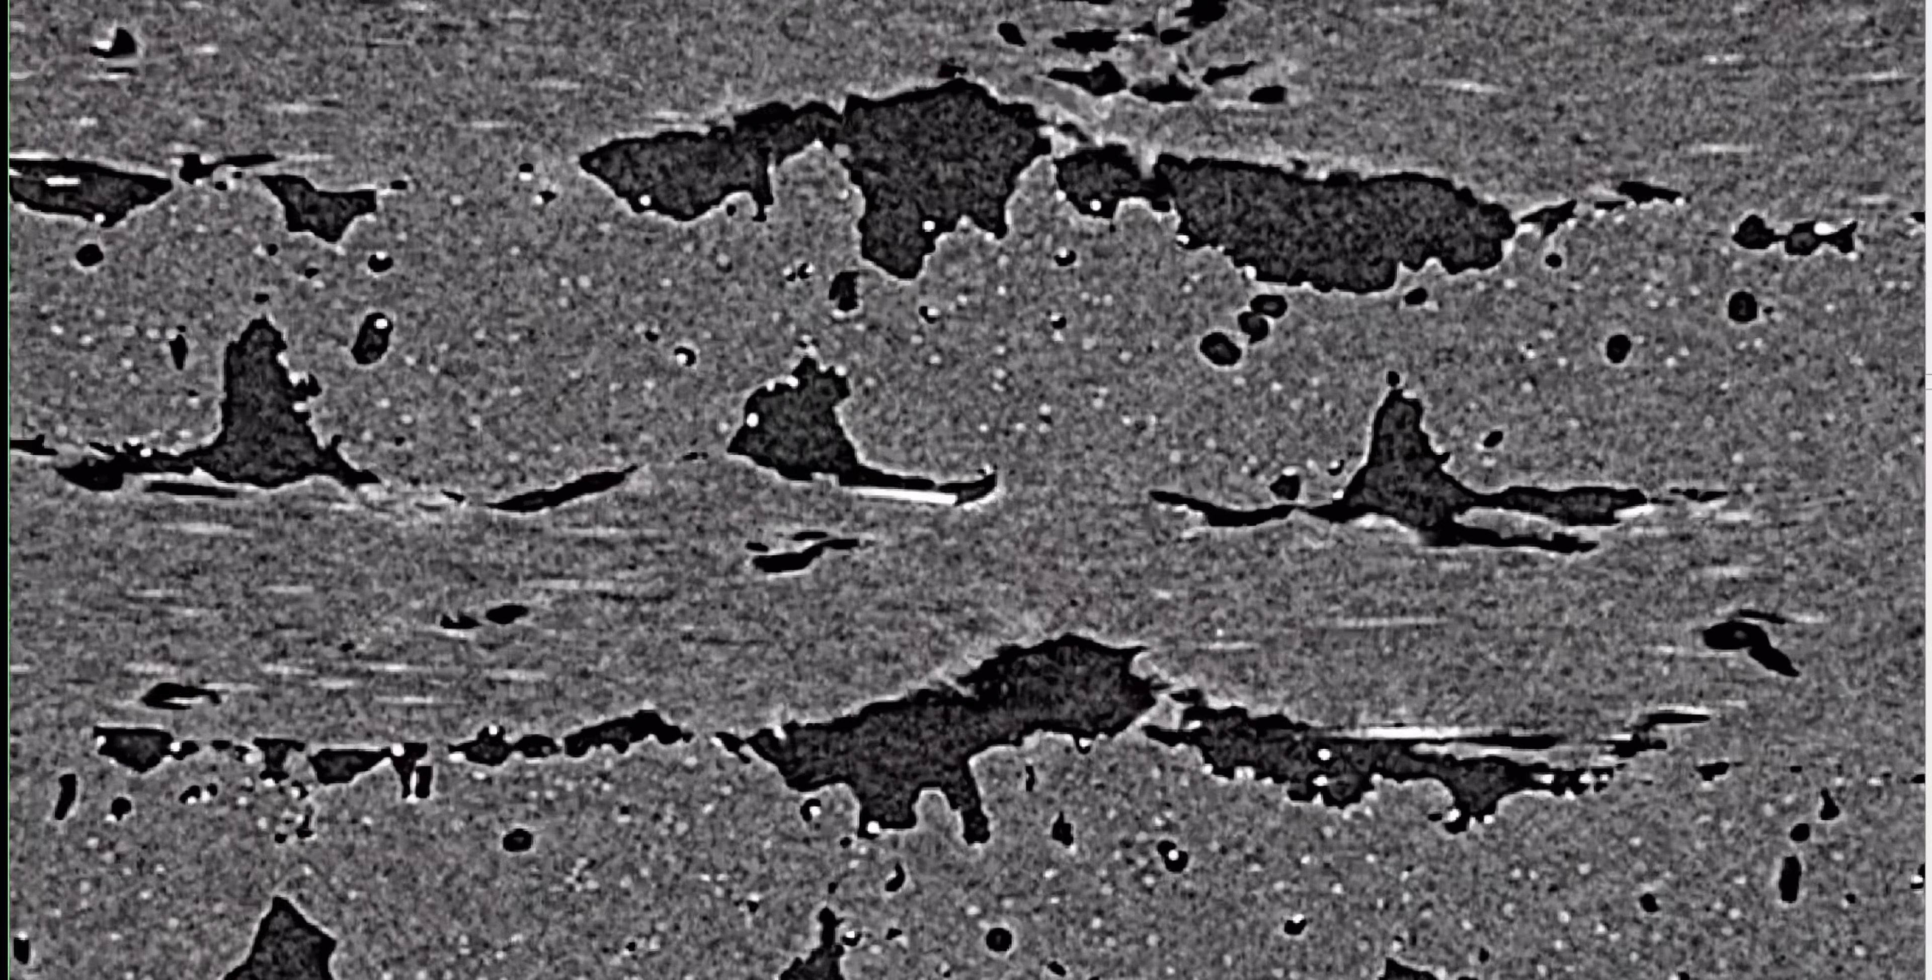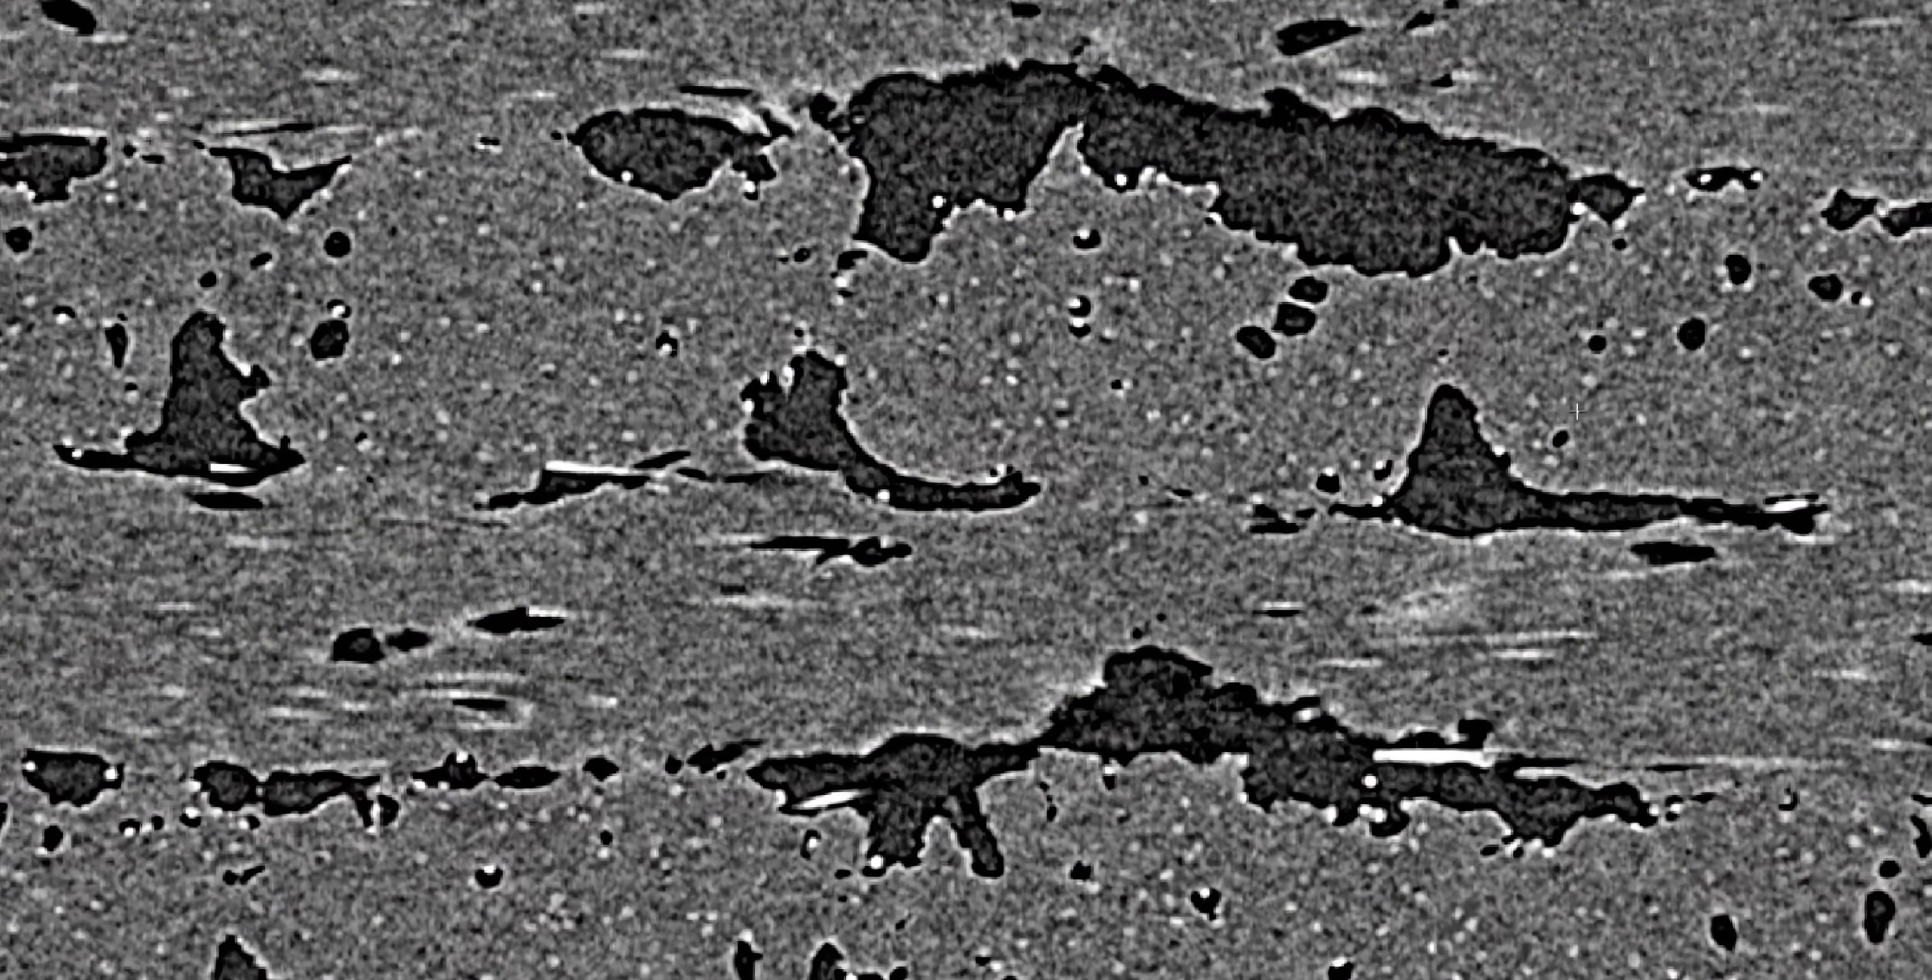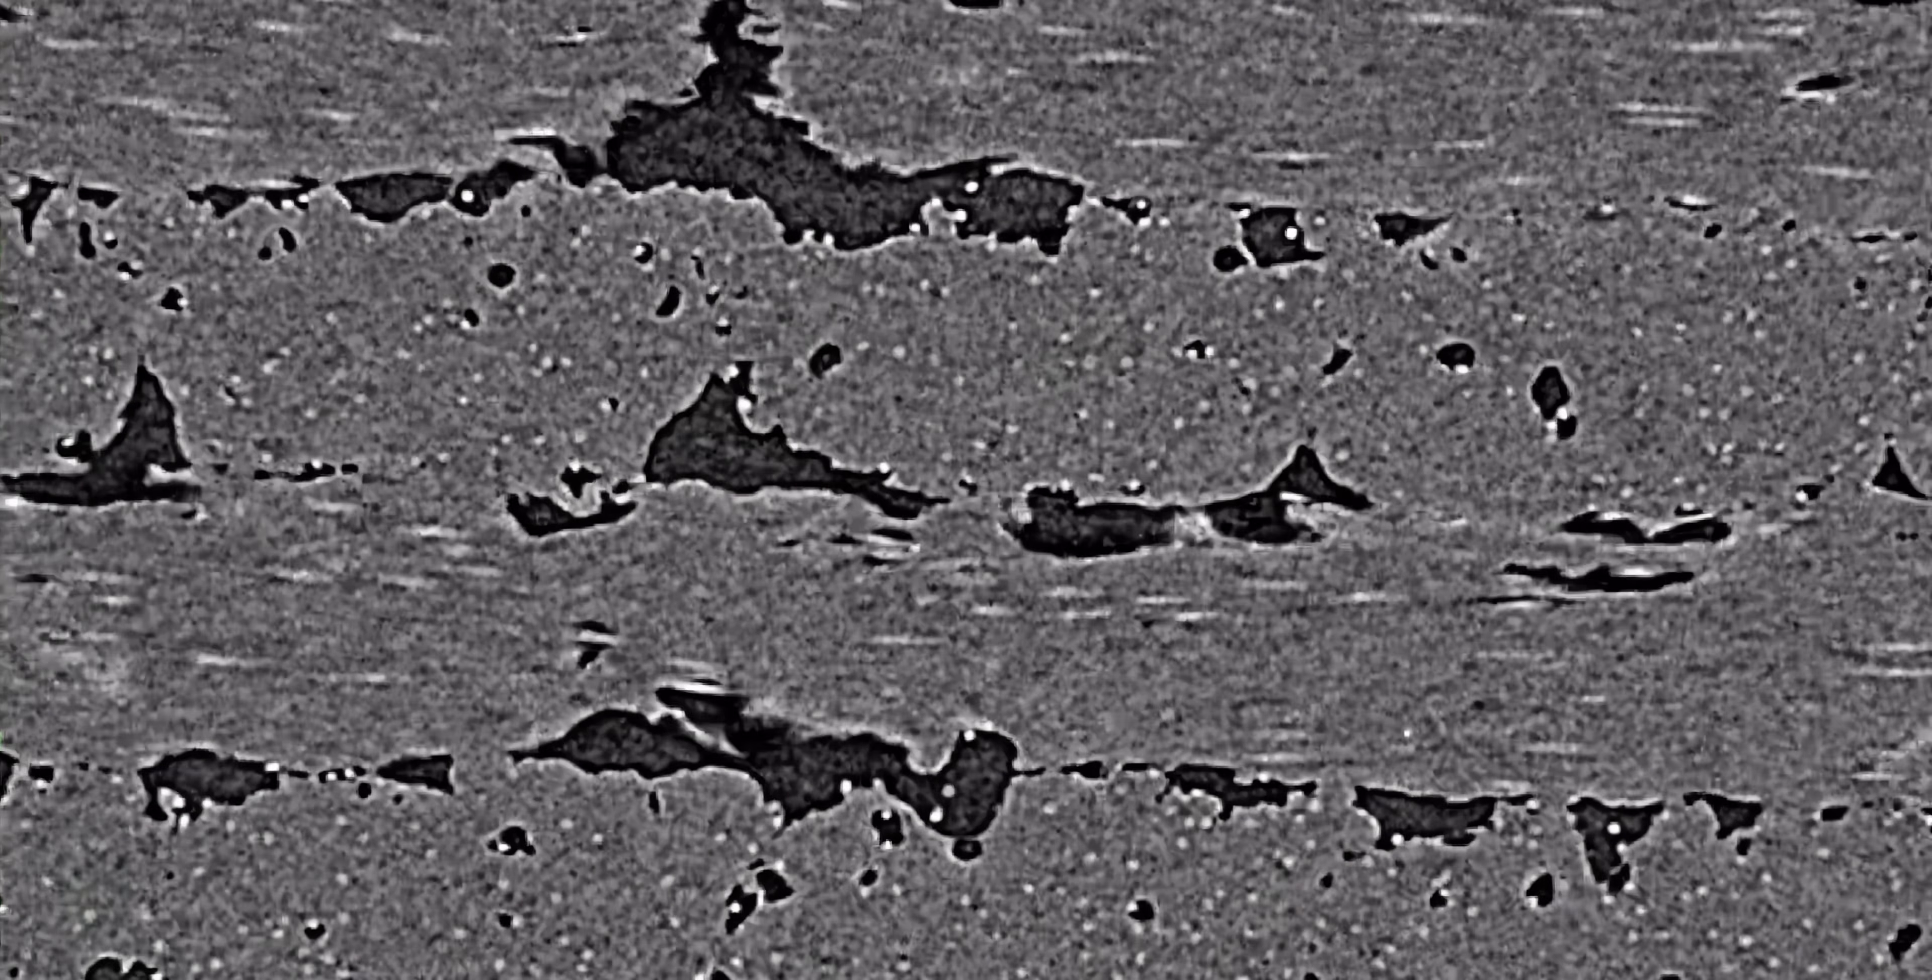Carbon fiber reinforced. I did the test, and I can still see that the fibers are in between printing layers that we already saw on our SEM images. But what I also saw is that the retraction from the polymer from the fiber itself—so the non-adherence and basically the voids creating around the fiber—it's real. You can actually see that the carbon fiber is in no way connected to the polymer itself. So basically, while cooling, the polymer retracts from it, and you could argue that reinforcing PLA with carbon fiber is the same as reinforcing it with air. You just have those bubbles and you have a loosely floating carbon fiber just inside of those voids.